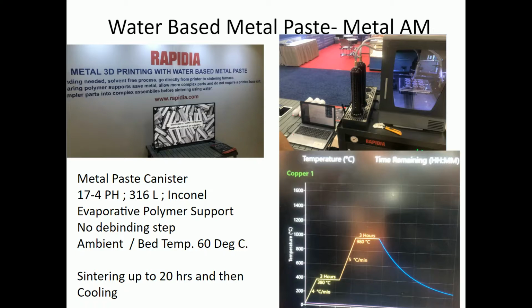The bottom lower picture shows the sintering cycle for a copper part. The sintering process lasts about 20 hours. The process involves slow heating at 4 degrees Celsius a minute up to 380 degrees C. A dwell cycle follows for 3 hours while the part is maintained at 380 degrees C. The temperature then ramps up to 980 degrees C at a rate of 5 degrees C per minute and is maintained there for 3 more hours. The part is then cooled down gradually to ambient temperature.